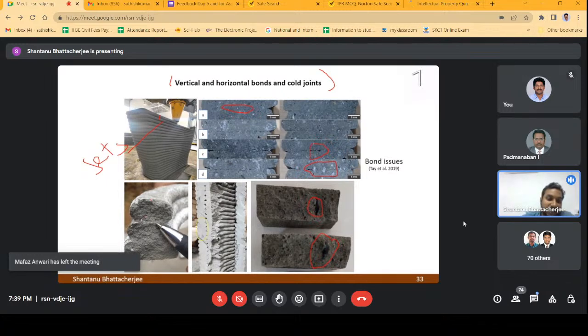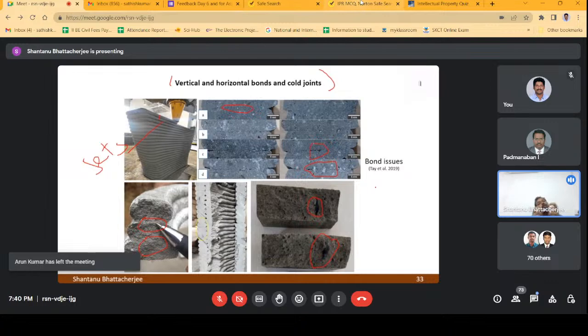So you can see that the layers here are not that bad because they were printed continuously, whereas you can get this kind of printing if the time gap is very high or you have a very fast setting material. If one layer sets before the next layer comes, you end up with a wide gap. So that is again a very important thing: when we as material people, or as structural or civil people, have to design, we have to have a proportion of setting in a way that it doesn't collapse while printing and doesn't form these kinds of gaps.